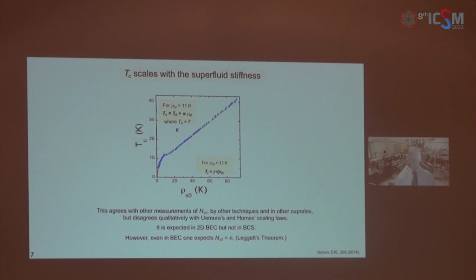The other point here is that the superfluid density and Tc track one another as a function of doping. This is also quite extraordinary because the zero temperature superfluid density in standard superconductors is equal to the total carrier density. In other words, it is a normal state property. It's independent of the strength of the pairing interaction. And hence, in BCS theory, superfluid density is unrelated to Tc. In contrast, Bose-Einstein condensation is driven by kinematics, which means that Tc is determined by the boson density alone.